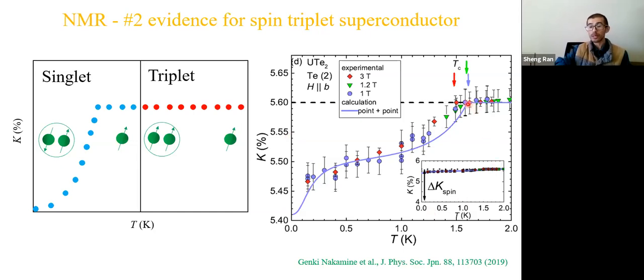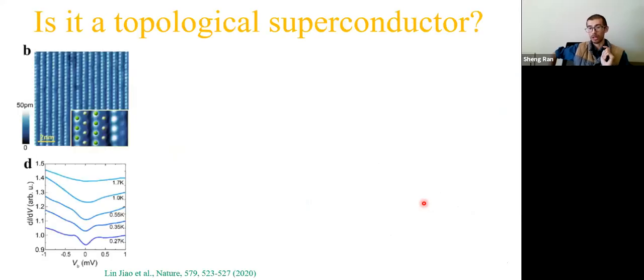Here, they did see a tiny drop, but this drop is not enough for a spin singlet pair. In this inset, for a spin singlet pair, the drop is supposed to be this large. So even though they see a drop, this is still consistent with a spin triplet superconductor. All right, so indeed, we found a spin triplet superconductor. Well, the next question is, can we find the physics that you promised at the very beginning?